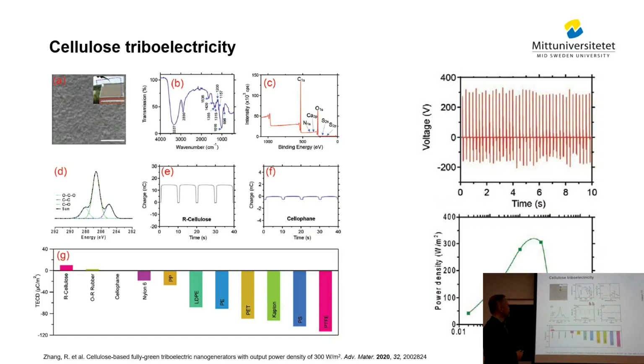So this was how it looked when we went into looking at the more structural things. We did the characterization with different XPS and FTIR, and then we measured how the cellophane and our cellulose worked, and we got a really high positive charge for the cellulose that we made. And if we look at the triboelectric series, we also saw that this was actually on the positive side compared to the other ones. So this is a triboelectric series that we did from our perspective, looking at cellulose.